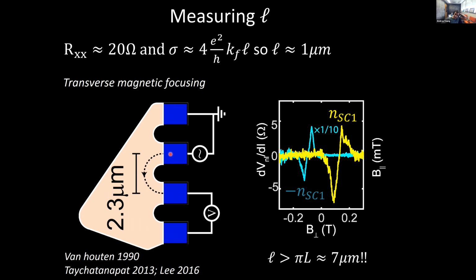And it turns out there's a simple experiment you can do here if you have ballistic electrons, where you drive a current, you put a voltage between these two contacts. But in order for a current to actually end up at ground from this source, electrons have to follow ballistic trajectories, and in a magnetic field, they can be focused into the additional contact. So if you set up a measurement like this, current will relax by bouncing off some boundary, but first it will be focused into this contact where it will relax its energy and generate a voltage.